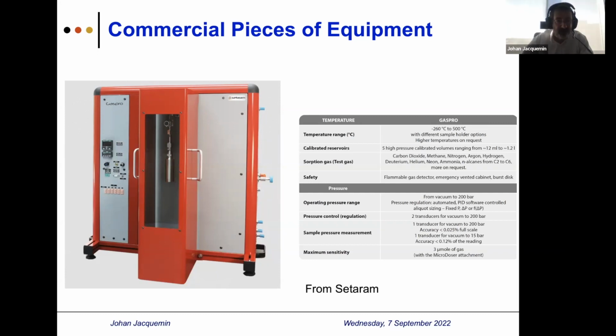Anyway, Setaram claims that this equipment is more sensitive. The limit of detection is 3 micromole of gas, and the cell ranges from 1.2 liters down to 12 milliliters, showing in many cases enough size to measure solubility within the sensitivity expected. Of course, this is mainly designed for working from vacuum to 200 bars.